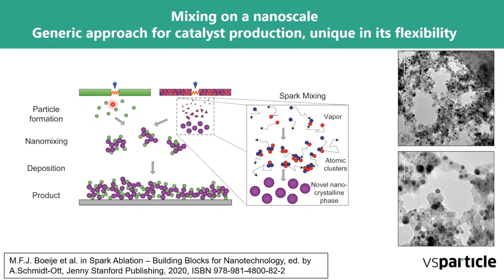The first spark may produce what is conventionally called the substrate of the catalyst, or the support of the catalyst, and the other one the active catalyst material. And when you deposit the particles onto a substrate, if you do that in the right way, then you have a porous material, and this porous material is then the catalyst.